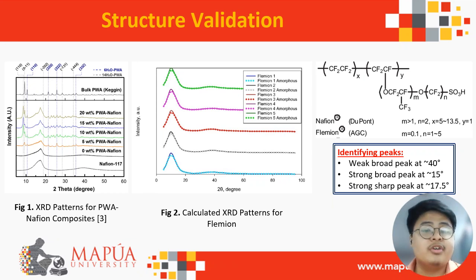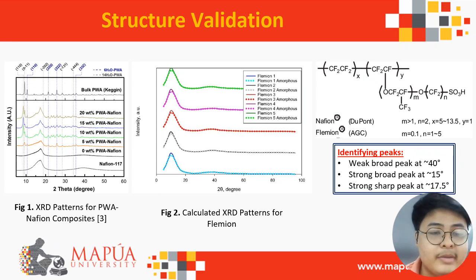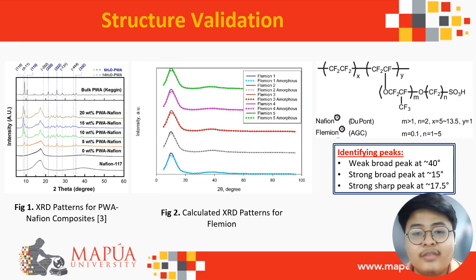Here in figure 1, we see the XRD patterns for PWA Nafion composites. What is important to us here is the XRD pattern at the bottom for Nafion 117. Here in figure 2, this is our calculated XRD pattern for Flemion. We can see a distinct similarity between Nafion and Flemion, with identifying peaks at the following 2 theta degrees. A weak broad peak at approximately 40 degrees, a strong broad peak at approximately 15 degrees, and a strong sharp peak at approximately 17.5 degrees. This tells us that the structure drawn is very similar to Nafion.